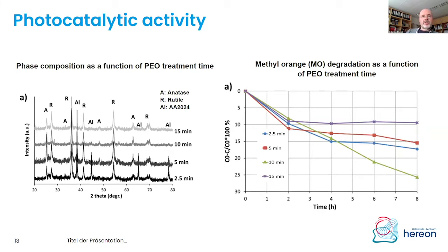So the main point here is that we want to know what phases we have in this. And we did diffraction patterns, and we were checking what happens when we increase the treatment time. The ratio between anatase and rutile is relatively balanced for shorter treatment times. But if we extend the treatment time, and here it was a constant current treatment, which basically means that we have more energy input with increasing treatment time, the ratio changes and rutile becomes dominant. And when we look at the degradation of methyl orange, which we were studying, there is no clear indication that with longer treatment time we get better properties for the catalytic activity on the surface. The optimum we found was for 10 minutes.